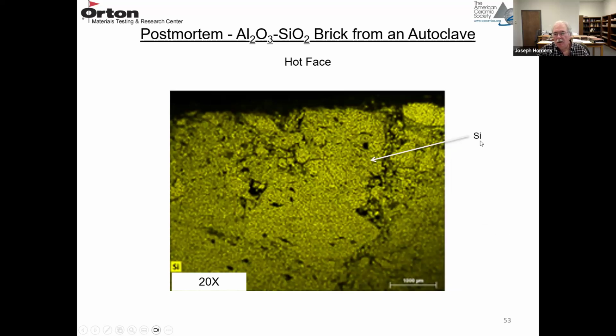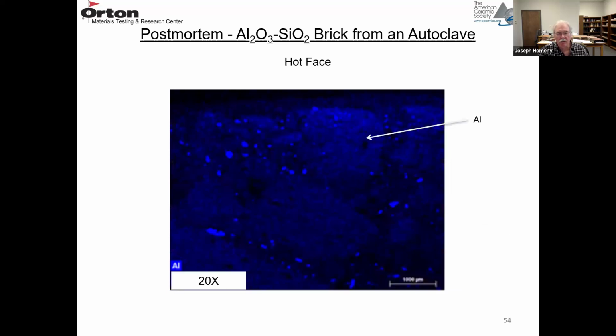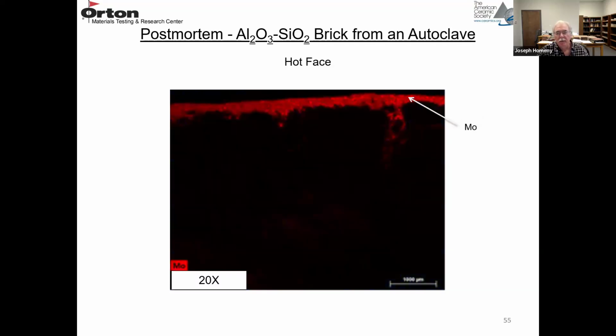So the yellow is the Si. So it's pretty uniform throughout the microstructure, whether it's the matrix or the coarser aggregates. The blue is aluminum. You can see the coarser aggregates. In the matrix, there are some little particles that are brighter, so that they probably had some alumina fines that were higher in alumina content in the matrix. And the red here is the metal MO. It's confined to the surface.